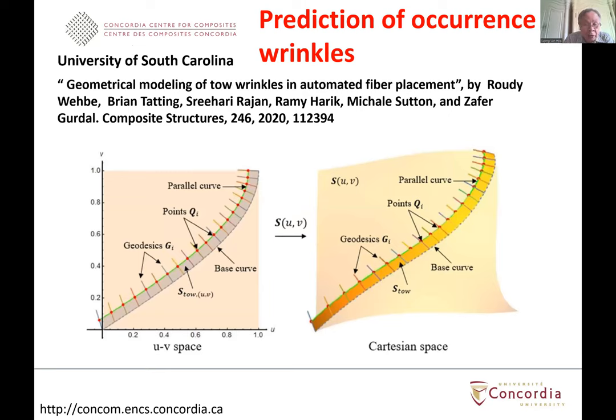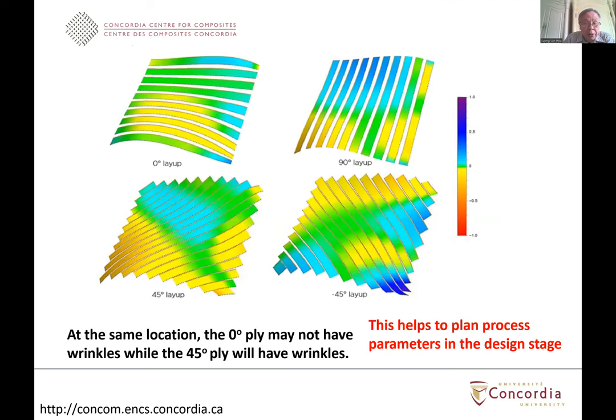They can predict whether you have some kind of wrinkle that may occur due to the mismatch between the actual path of the tow and the surface of the part. So by using this method, they were able to generate a picture to show whether there will be wrinkle forming or not. In this picture, the green line shows the place where you don't have any wrinkle, and the yellow location shows the location where the wrinkle occurs. And they can do that for the layers at 0 degree, 90 degree, 45 degrees, and minus 45 degrees. You can see that for the same kind of surface geometry, at some location for the 0 degree layer, you don't have any wrinkle, whereas at 45 degree, you may have wrinkles.